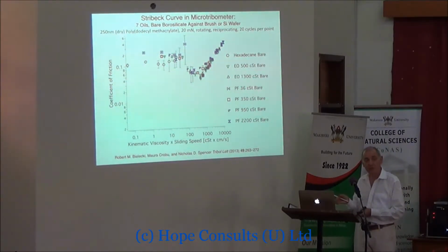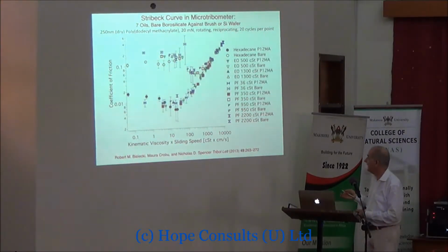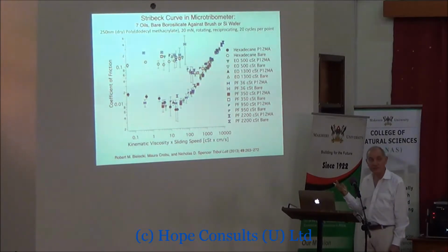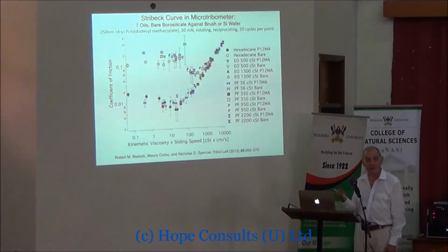Now I'm going to compare that with putting the oil-compatible brushes that we grew on the surface. And you can see an enormous decrease. This is a log scale here. So we've got more than a factor of 10 decrease in friction coefficient. And what's also interesting is this hydrodynamic regime gets extended and then goes straight into a low friction regime. So there's no mixed regime anymore because there's no hard contact going on. We just go straight from hydrodynamics out here to a fluid film that is caused by the behavior of the